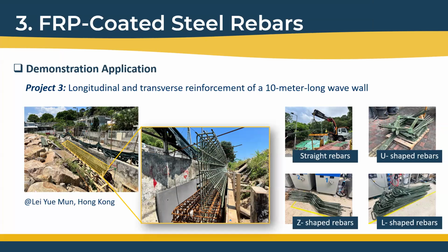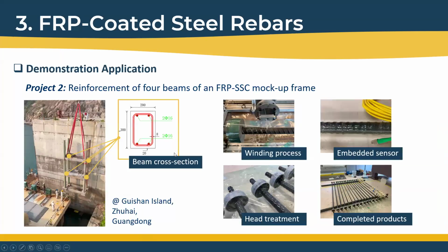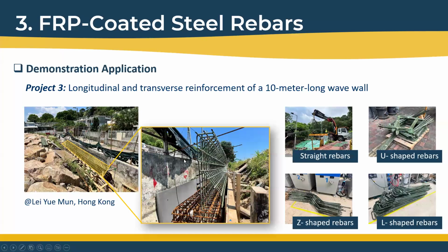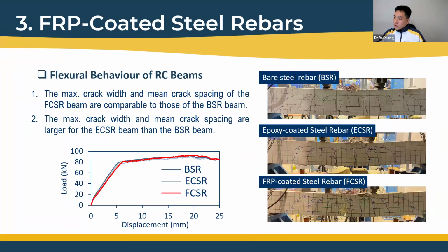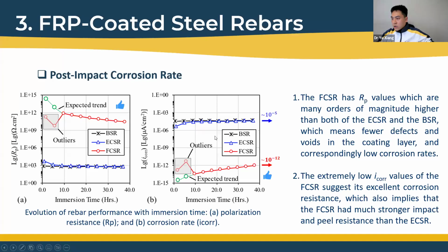The next question: how to detect corrosion through electrochemical methods in such rebars when the epoxy itself is non-conductive? The resistance may always be high, and you presented different shaped bars in project 3—were those shapes formed prior to FRP coating, or did you bend the rebars after coating? For epoxy coated steel rebar, normally if the coating layer is in a very good state and you perform an electrochemical test, it is non-conductive.